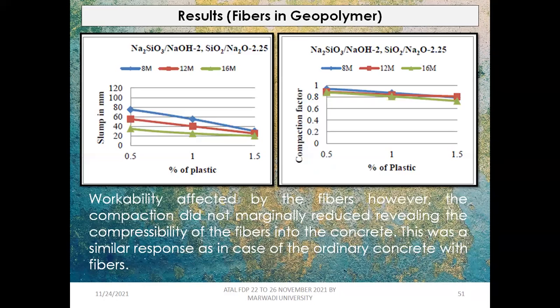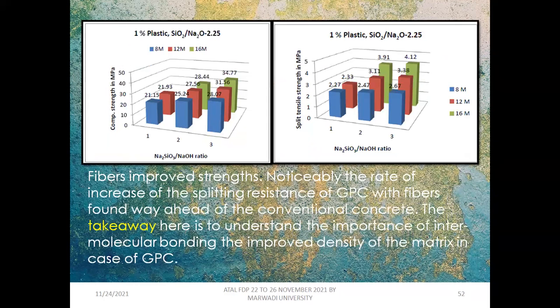These are some of the results: slump of the freshly made geopolymer, compaction factor, then compressive strength and splitting tensile strength of the mixtures. You can see here there is a variety of molar content and a variety of plastic ratios, like the alkaline liquid itself, which we can produce in many varieties and proportions.